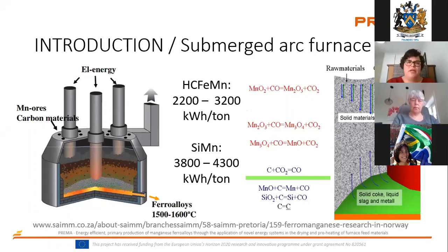So for those of you who are not familiar with ferroalloy production using submerged arc furnaces, this is a slide that was taken from a presentation by Professor Merete Tangstad. And what you see on the left-hand side is a submerged arc furnace. The electrical energy is supplied via three what they call Söderberg electrodes. So these electrodes are very, very wide in diameter. 1.6 meters is not a funny number, it's a typical number. And the electrodes need to be baked while production of the alloy is taking place. So it's quite a complex process to manage your electrodes as well as your process itself.